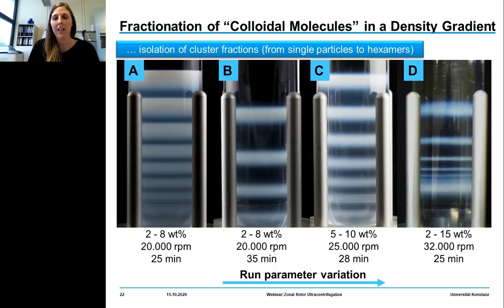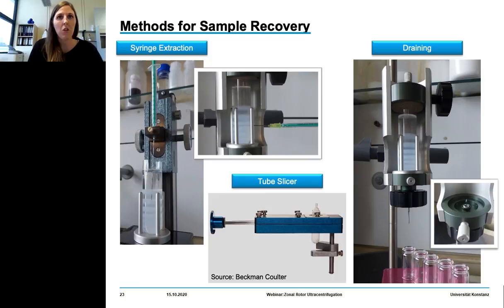We optimized the strategy for sorting colloidal molecules. Here you see centrifuge tubes with banded colloidal molecules, all well-banded in discrete bands. We probed different sets of experimental parameters and also applied different extraction strategies. For instance, we can use a cannula and collect the particles from above.